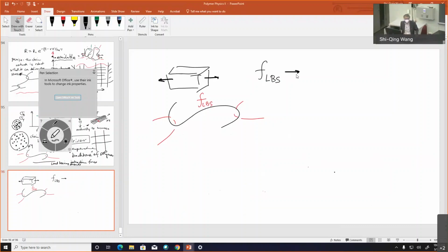remember, unlike the melt state, there's very little relaxation going on. Everything's frozen. So this actually means the force arises much more readily. The tension in the chain, because it doesn't have a chance to relax. Don't need to speak about Weissenberg number. That would be too high.